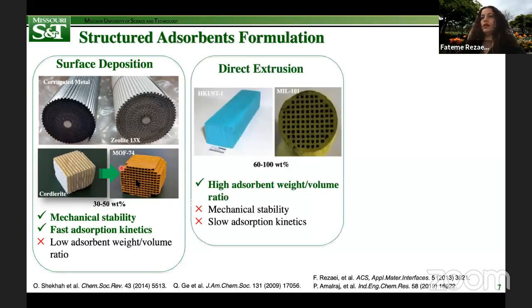The active adsorbent may be deposited on the walls for the first step, but in another approach, the active adsorbent could be directly extruded through a direct extrusion technique, by which it could be shaped to a desired structure, like these two MOF monoliths that I'm showing you here, HKUST-1 and MIL-101, where the large portion of the monolith is made of active material, unlike the previous technique, with the rest made up by binding agents or plasticizers to impart required mechanical integrity.